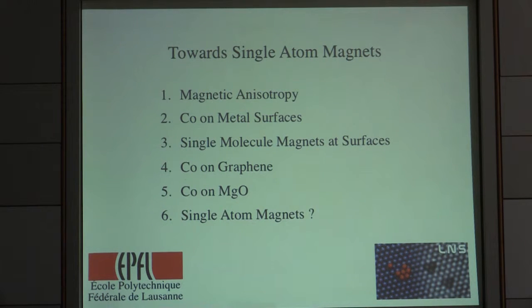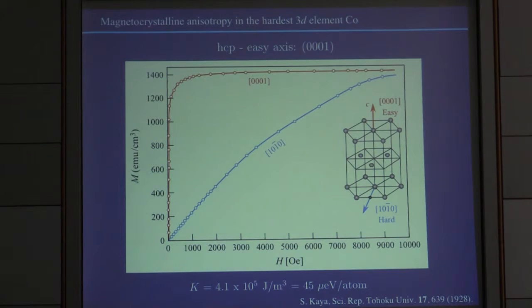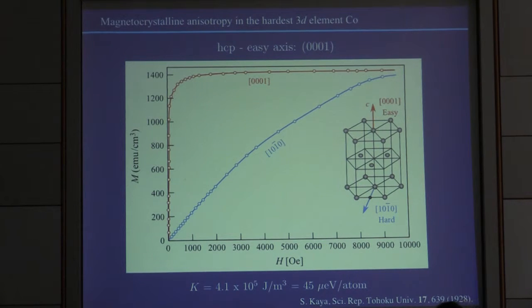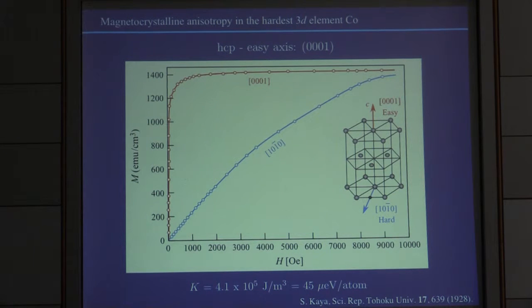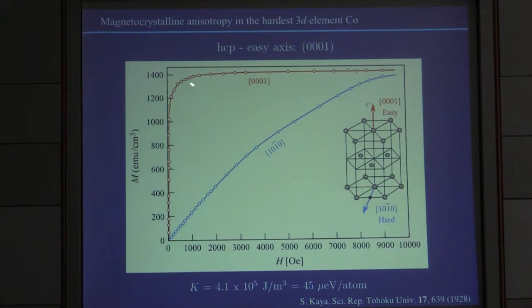The talk starts with an introduction to magnetic anisotropy. This is something that most of you in the audience don't need, but I recall it because it's also important for the numbers. One of the ingredients if you want to make a stable magnet is that you want to have a high magnetocrystalline anisotropy. I bring up this measurement that dates back almost 100 years, where people measured the magnetization of cobalt bulk along certain crystallographic directions. If you magnetize cobalt along the 0001 direction, which is along the C axis of the HCP lattice, you can saturate it at relatively low external magnetic fields.